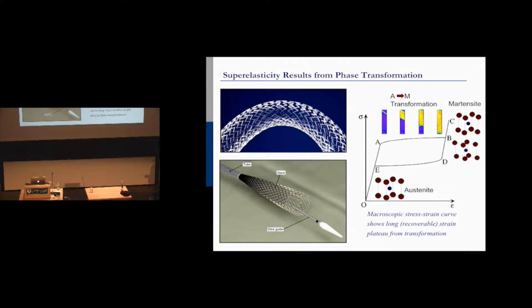And what's happening is when you pull this little strip, as you're going along the stress strain curve, you get martensite that nucleates. The austenite is a B2 cubic, and the martensite phase is called a B19' monoclinic. It's basically a tetragon that's skewed. So it's a displacive transformation, so you're not doing any diffusion. All you're doing is the atoms are going like this and like that. Now you can imagine there's actually different variants of martensite. If you're going cubic to tetragonal, that tetragon could happen in a couple different ways, right? You could either go like this, or like this, or like this, or this. Those are all energetically the same. Those are called variants of martensite.